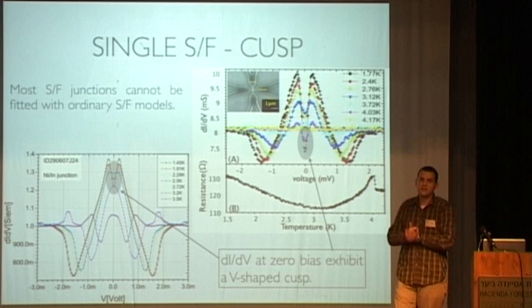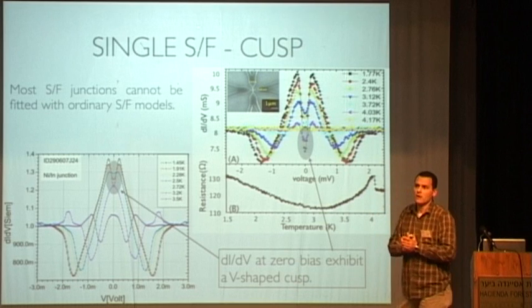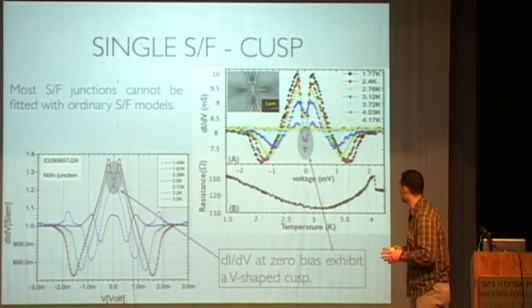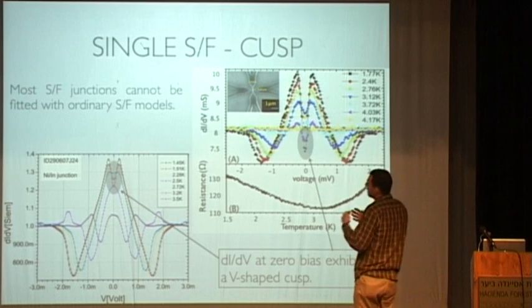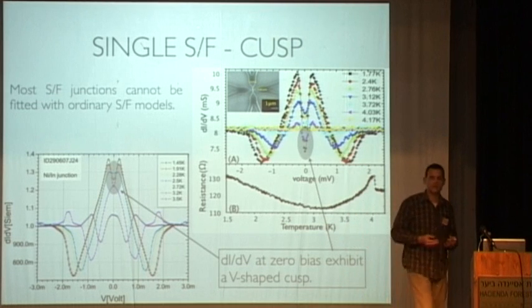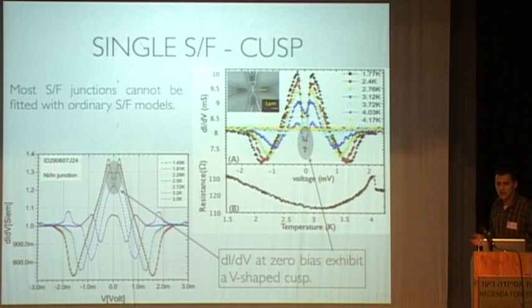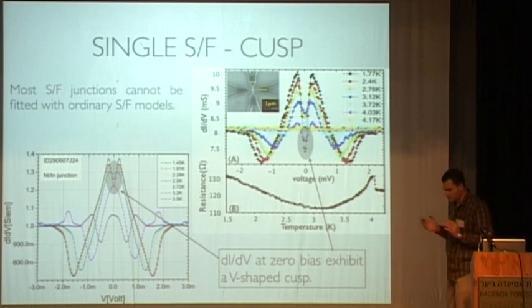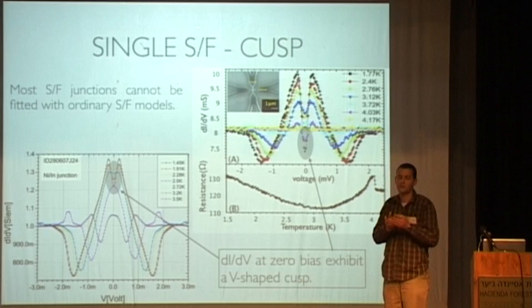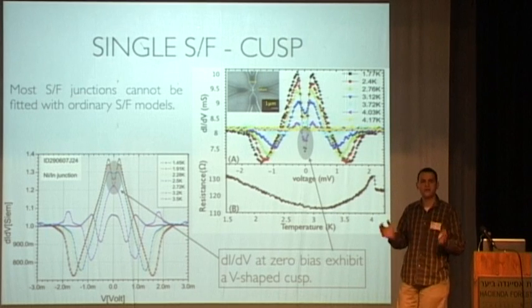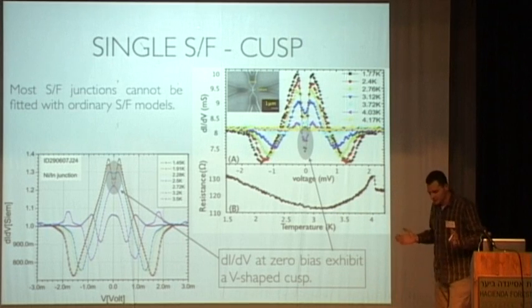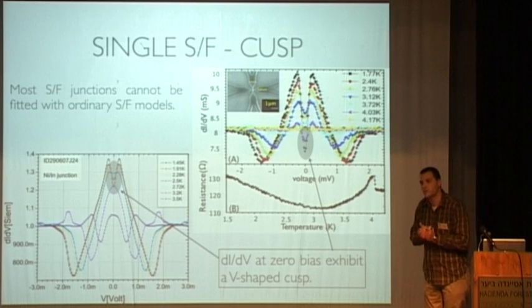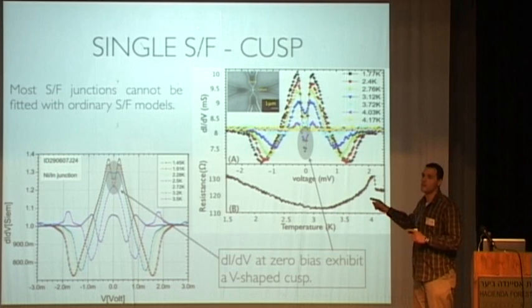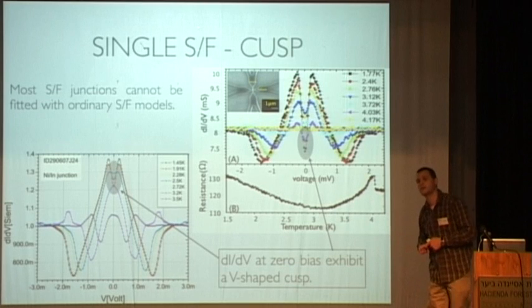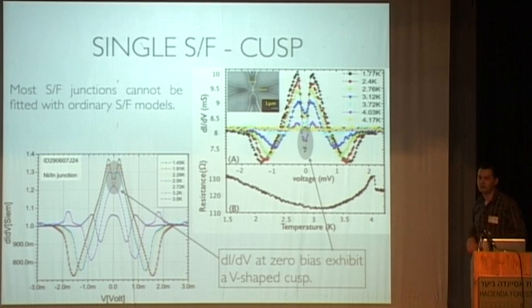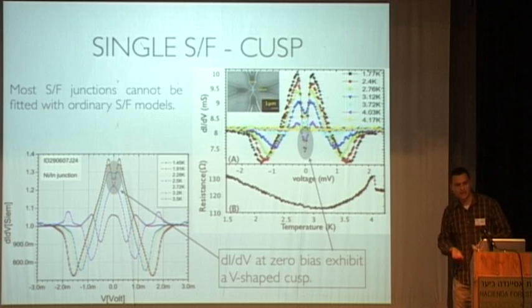And the V-shape in the middle is a fingerprint of an anisotropic order parameter, or something special about the superconductivity in the indium. And I want to remind you that we are measuring indium. Indium is a type 1 superconductor. It is ordinary in all matters. It has a very isotropic order parameter, but not here. Here, when you put it in contact with cobalt, you see it has anisotropic nature. Maybe it's a triplet, maybe it's something else.